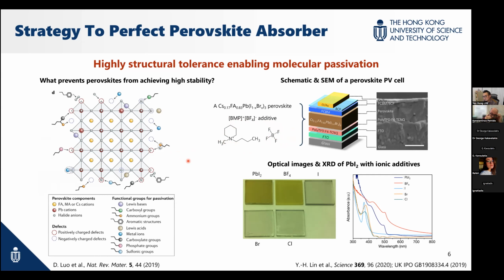So back then we did some simple experiments, just trying different ionic additives. The same cations, but different anions. The anion here is BF4, but the others are iodide, bromide, and chloride. Something interesting is that when we mixed them with one of the perovskite precursors, which is iodide, it forms a complex. The compounds that form complexes are the ones that contain halides. So when we add additive, sometimes it forms this kind of complex. It's a structure we don't want. It would destroy things later on when we add all the different precursors to form the perovskite structure. BF4 somehow doesn't form this kind of strong coordination complex, so it becomes a good candidate.